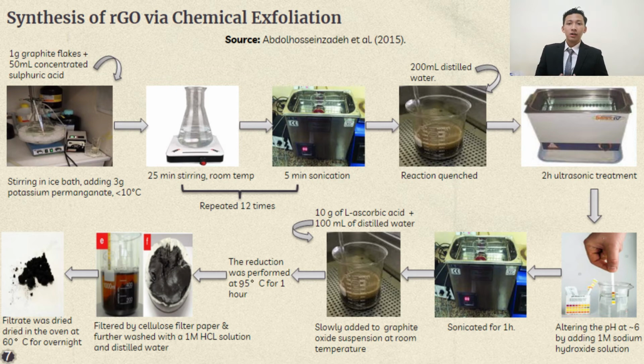The mixture is then stirred at room temperature for 25 minutes, followed by 5 minutes of sonication in an ultrasonic bath. After repeating the stirring and sonication process 12 times, the reaction is quenched by adding 200 ml distilled water, followed by another 2 hour ultrasonic treatment. After adjusting the pH value to around 6 by adding 1M sodium hydroxide solution, the suspension is further sonicated for another 1 hour.